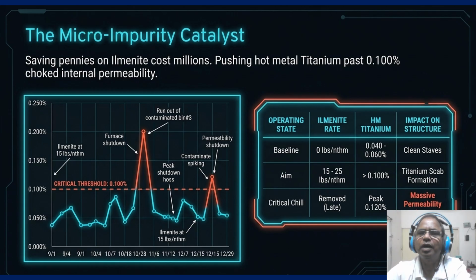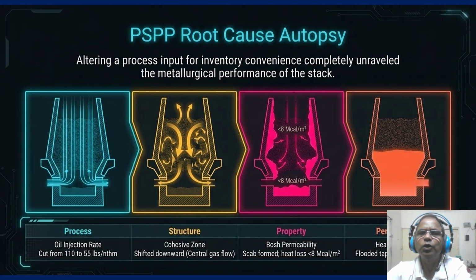So, coming to the PSPP root cause autopsy. Let's walk through the four phases of this metallurgical unraveling. It started with the process, for inventory convenience. The oil injection rate was slashed from 110 to 55 pounds per ton. So this fundamentally altered the structure. The cohesive zone shifted downward and gas flow turned purely central.